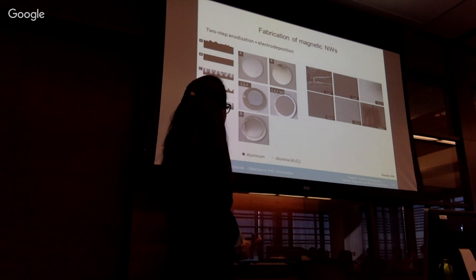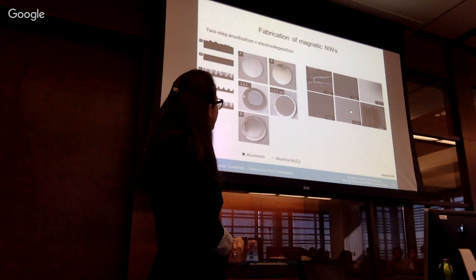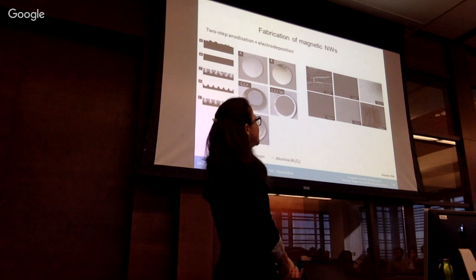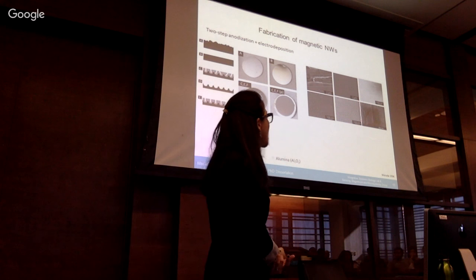However, the outcomes, this is C, this is E, are very different. So here we do have an ordering, we do have a uniform pore size, and this is actually the template we use to deposit the wires. And this one corresponds to a cross-section image of our sample. You can see how parallelized the pores look.